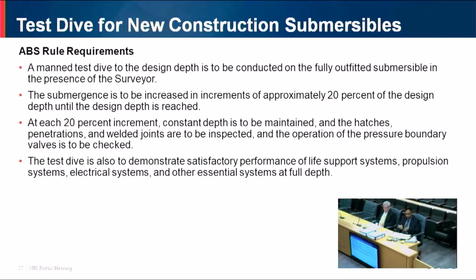So then we come to the ABS rule requirements for test dive of new construction submersibles. So after the pressure hull is built and it is fully outfitted, we conduct a test dive. Okay, so before passengers get on the submersible, you have to do a test dive in the presence of the ABS surveyor. So how do you do this test dive? Okay, you start diving and you increase your depth at 20% increments. So you first dive to 20% of your design depth, you stop, and then you will start internally inspecting all your welds, all your hatches, you will inspect your windows, and you will check your pressure boundary valves, make sure there are no leakages, okay?